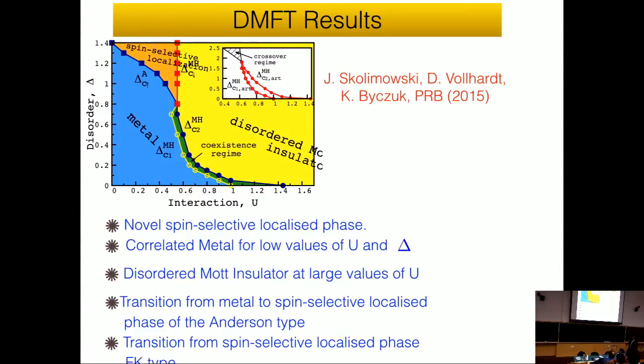As you increase the interaction strength, of course, you sit at a small disorder, you increase the interaction strength, then you go through a Mott-Hubbard sort of transition, and this, of course, is where the coexistence regions actually shrink. This can be understood by disorder effects, because once you have disorder, it tends to suppress the first order transition, and that's possibly the reason why this goes through.